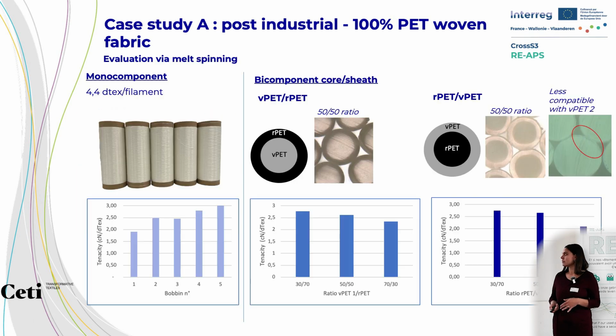on our melt lines. In terms of the evaluation via melt spinning, this specific fabric was processed and spun, and then we moved to core-sheath configurations. As I mentioned before, the virgin PET is either in the center or in the outside of the polymer. You can see the 2 different configurations in the pictures here. One of the main takeaways: we saw that the virgin polyester would define the mechanical properties component.